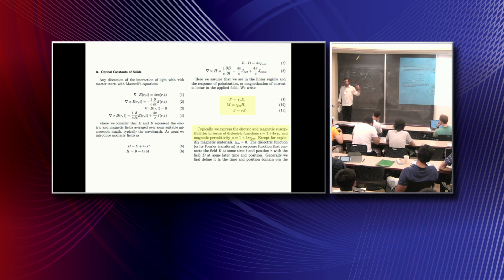Generally, when we measure reflection from a sample, it's going to be a number. It's going to be a good reflector or a bad reflector, and this is going to be a frequency-dependent quantity. What I really want to know is the complex conductivity, which is a complex quantity, but I'm just measuring a scalar quantity, the reflection coefficient. I can't figure out what the complex conductivity is unless I know the reflected wave's phase at the same time. So how the heck can I do that? Well, there's a Kramers-Kronig relation. If I know the reflection coefficient for all frequencies, I can get the reflected wave's phase, and then I can go ahead and apply the Fresnel equations.